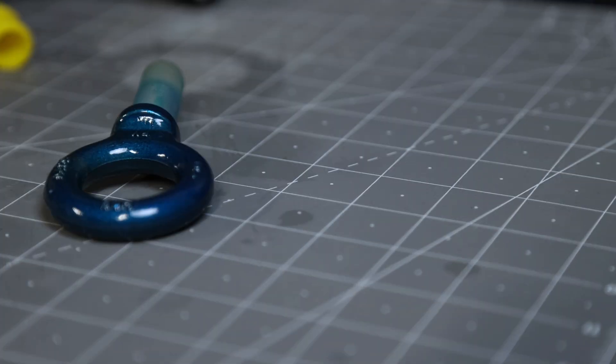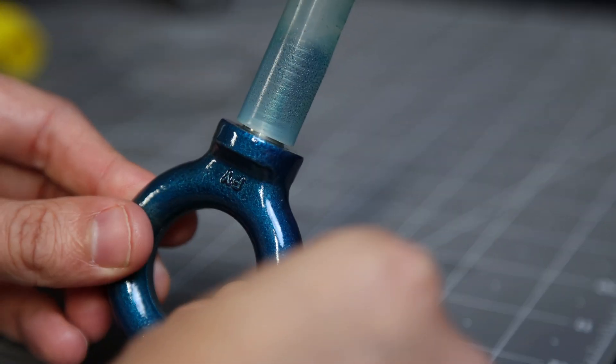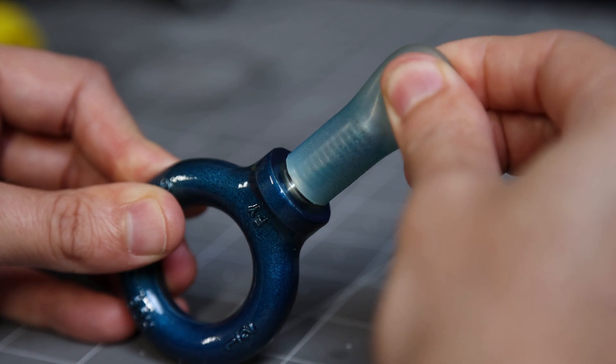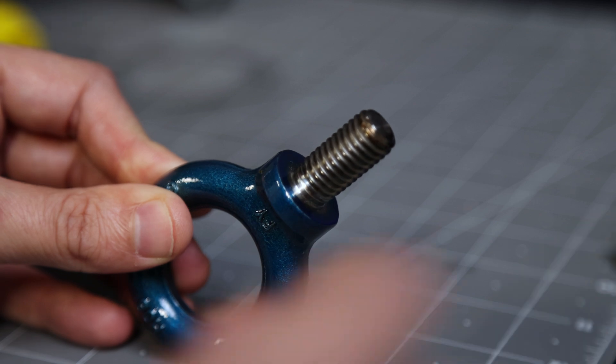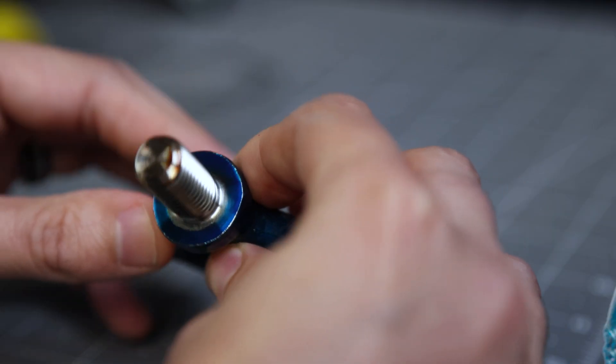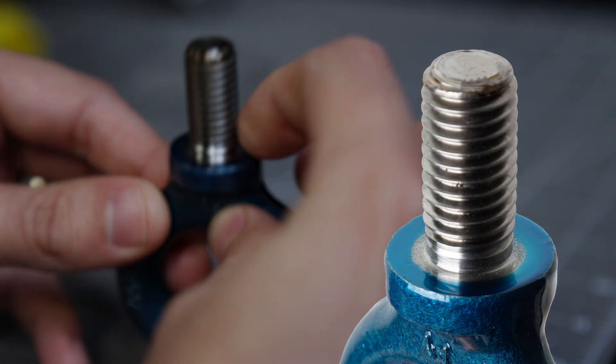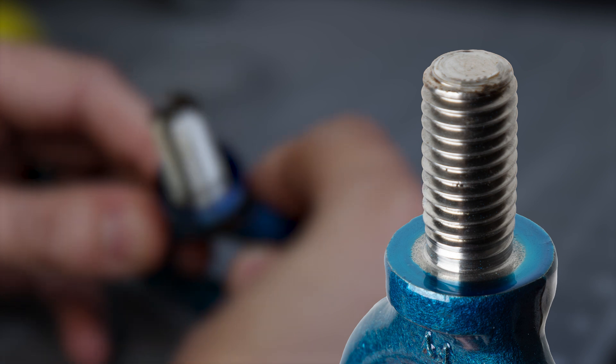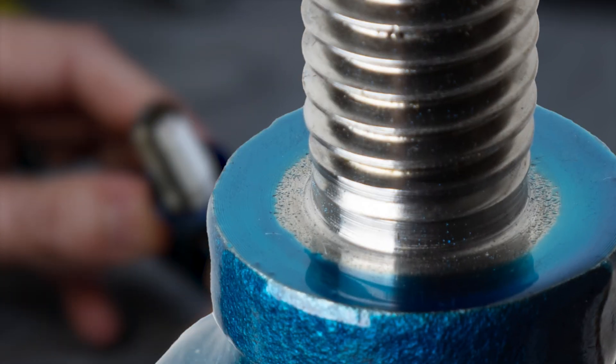Now it's time for the cap that was slightly above the base. A few things that I noticed with this was that there was no bridging at all. But the main drawback with this method was that there was inconsistencies with how far the powder made it under the cap.